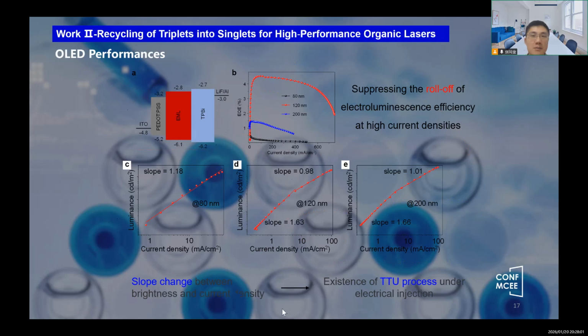Furthermore, by introducing the above low-threshold gain materials into an electroluminescent device and optimizing the device structure, we obtained a maximum external quantum efficiency of 4.5%, exceeding the theoretical EQE limit of typical fluorescent OLED devices.